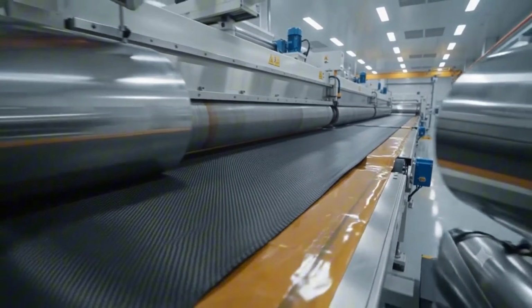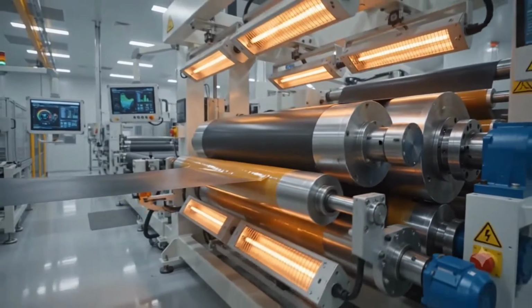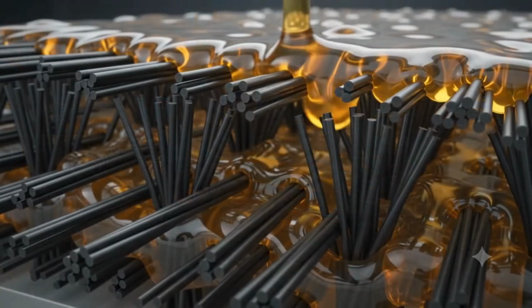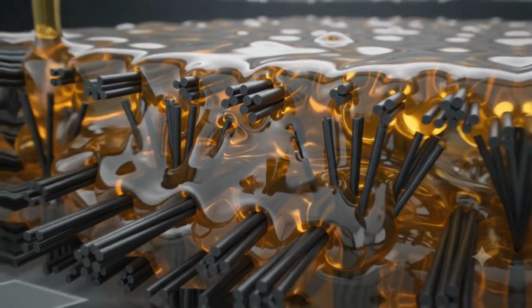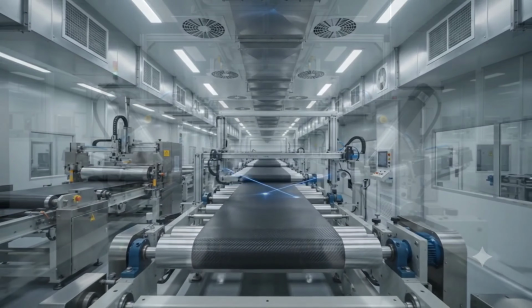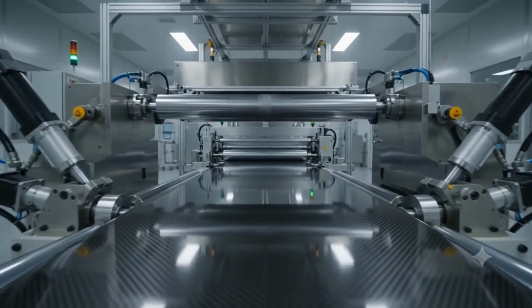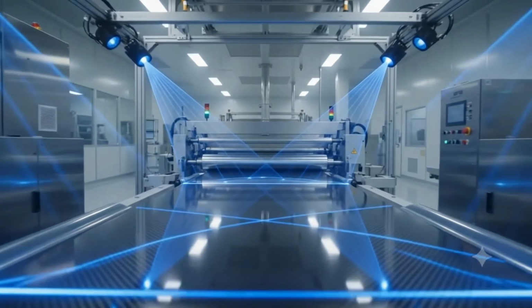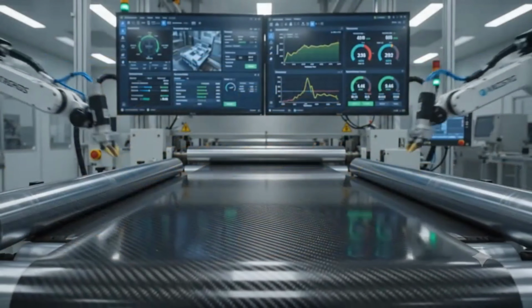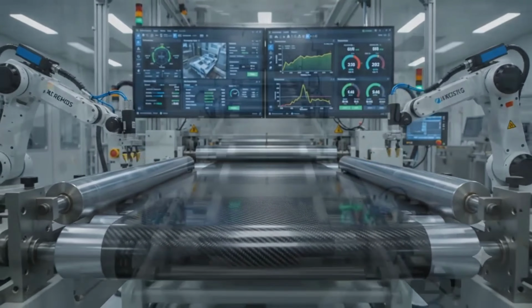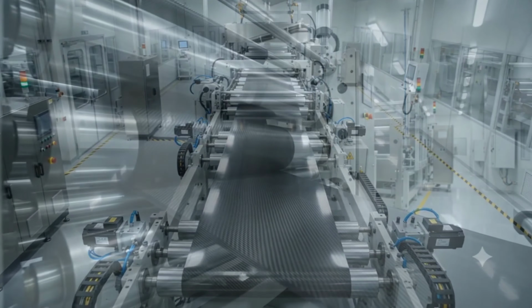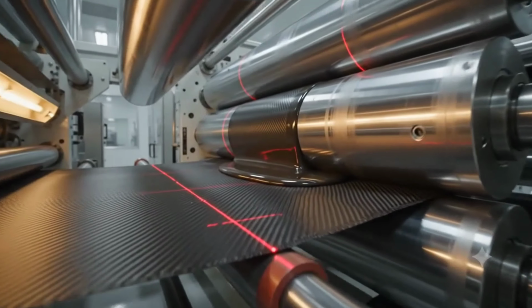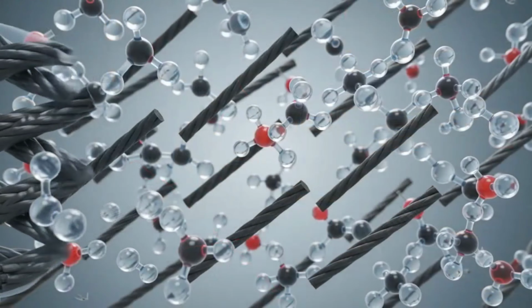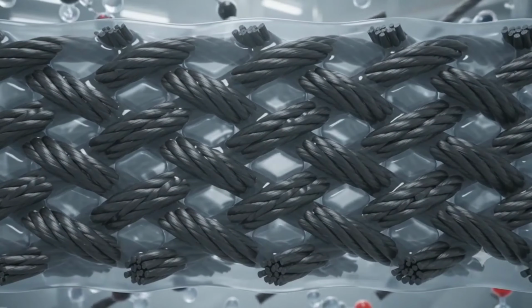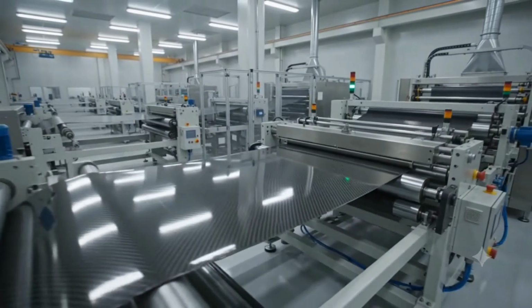Heat and pressure bring resin and carbon fiber together, creating the first stage of prepreg, where every filament begins its transformation into an advanced composite material. Precision calibration ensures every sheet of prepreg meets exact aerospace specifications, with perfectly balanced resin content and uniform thickness throughout. Every carbon filament is completely saturated with aerospace-grade epoxy, creating a perfectly balanced prepreg ready for the most demanding engineering